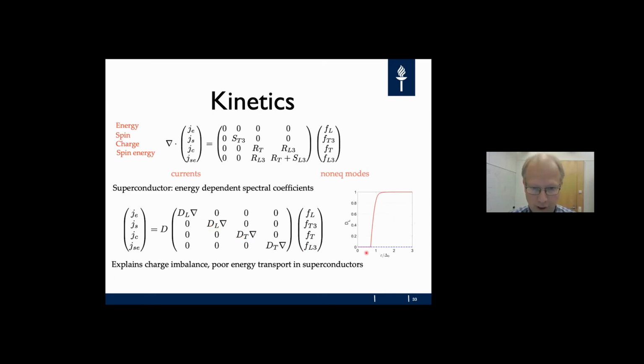For example, the energy transport dL is quite simple—in this case it's basically a step function, here a little bit broadened. This tells us that below the gap, there is no energy transport in a superconductor because you cannot have entropy transport inside the gap. This describes the poor energy transport in superconductors.